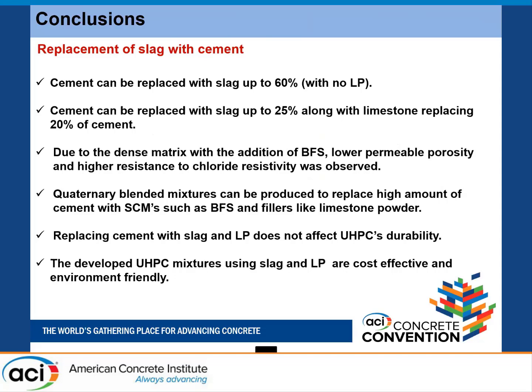Quaternary blended mixes can be produced, like cement, silica fume, slag, and limestone powder. That's the best combination we're thinking, and we have to move forward. And durability is not at all adversely affected by the use of slag in combination with limestone. The final UHPC product with a quaternary blend or tertiary blend is a cost-effective and environmentally friendly UHPC that can be produced with your locally available materials and can be widely used in your structural applications.